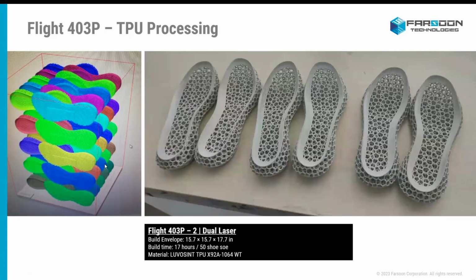With the flight system, we were able to pack the build envelope with 50 shoe soles, and we were able to accomplish a full build in 17 hours. Which, if anyone has ever processed lattice structures in SLS, can attest to the long layer times just because of the complexity of the lattice designs. There's a lot of laser jumps. So not only were we able to take advantage of the ease of processability with fiber lasers, but also the increased scan speeds.